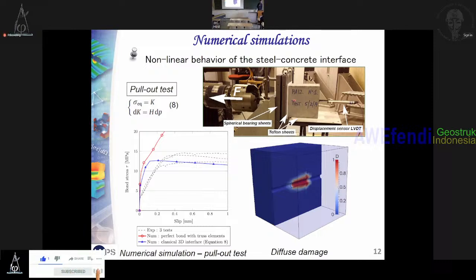If you plot here the evolution of the force or the bond stress with respect to the slip, you have in black the experimental results.